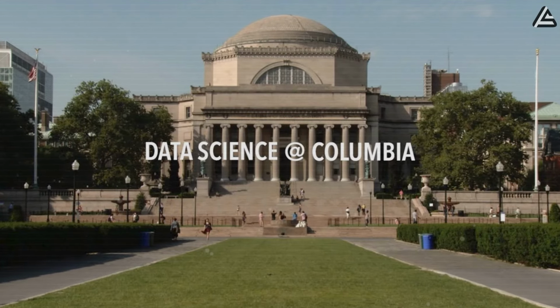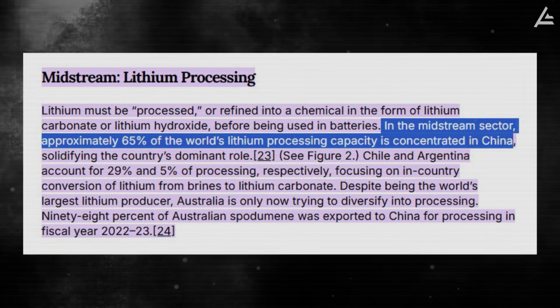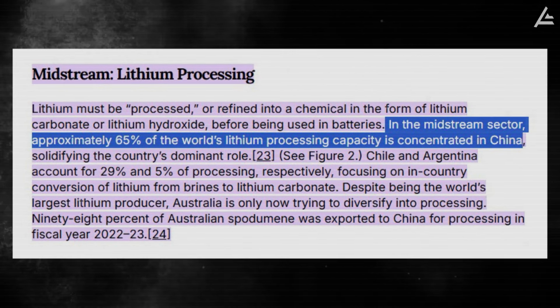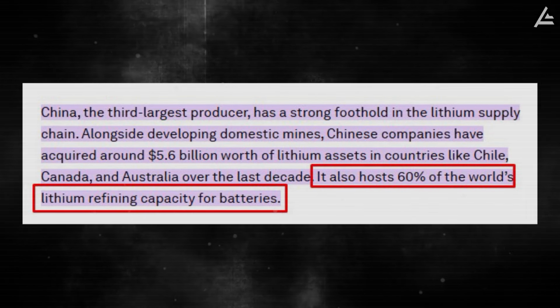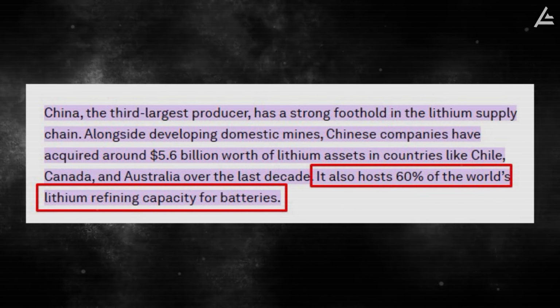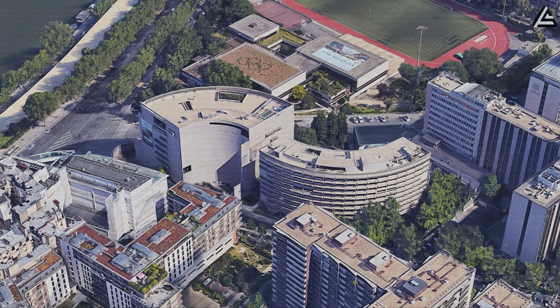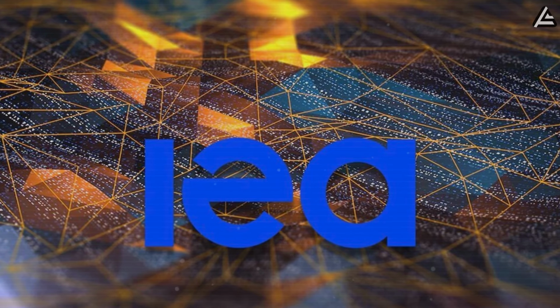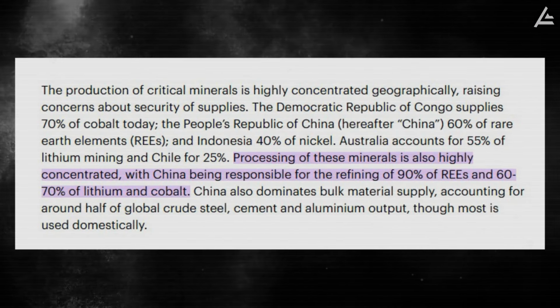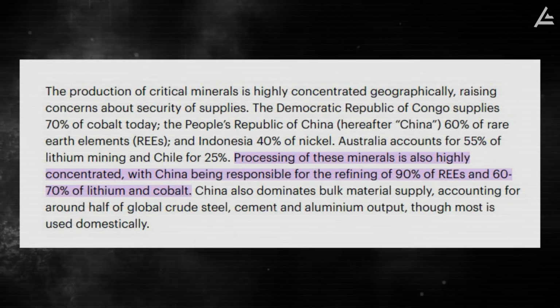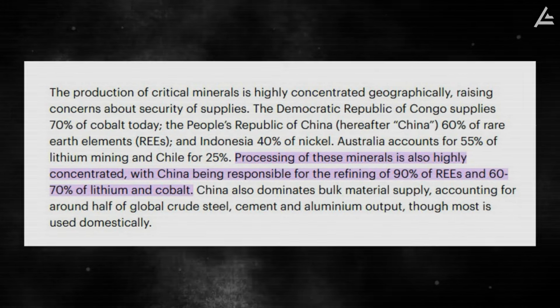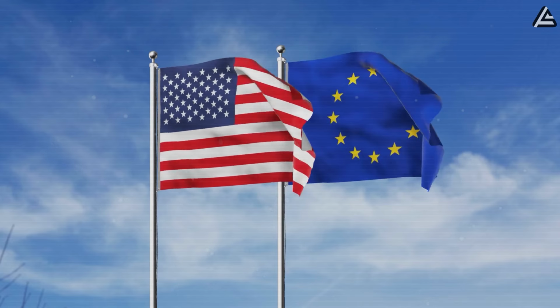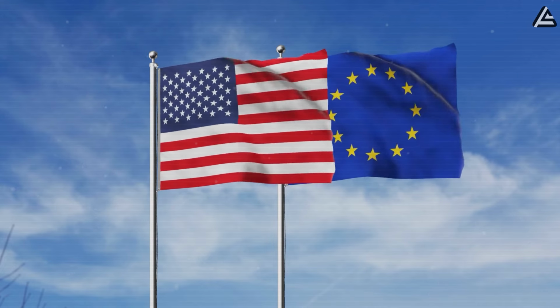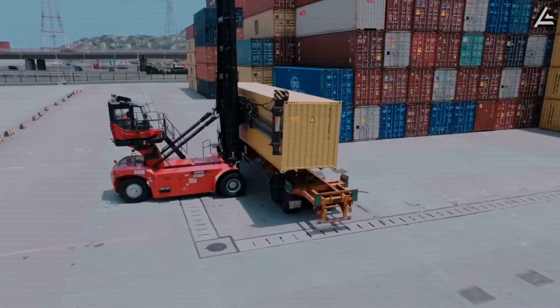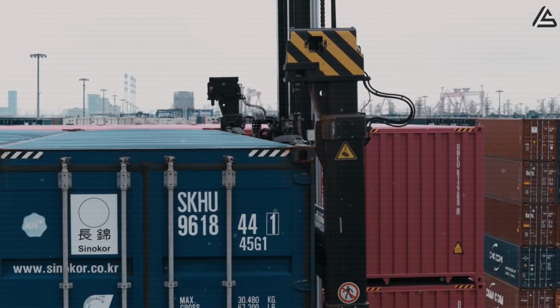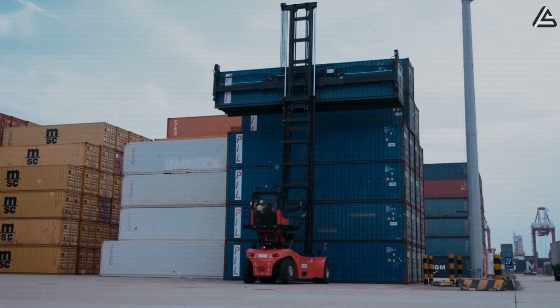According to Columbia University data, around 65% of the world's lithium processing capacity is concentrated in China. Another source states, China accounted for more than 60% of battery-grade lithium refining capacity. The International Energy Agency reports that for key clean energy minerals, China is responsible for 60 to 70% of lithium and cobalt refining, and processes around 90% of rare earths. This dominance illustrates why US and European policymakers are deeply concerned. Electric vehicles risk being tied to China's strategic leverage, just as previous energy systems were tied to oil-rich states.